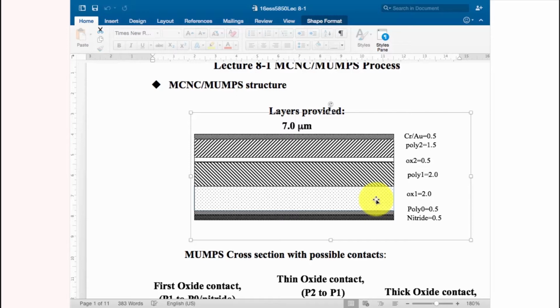We have learned about the surface micromachine process a couple months ago, regarding how to deposit material layer by layer, and by using a sacrificial layer to separate them. And then at the end, we take out the sacrificial material and obtain the structural material. Then we get the final released structure. This kind of structure has been developed for a couple years until they finalized the thickness of each layer. Polysilicon 1 is around 2 microns, pretty thick. The second polysilicon is 1.5 micron, a little bit thinner.